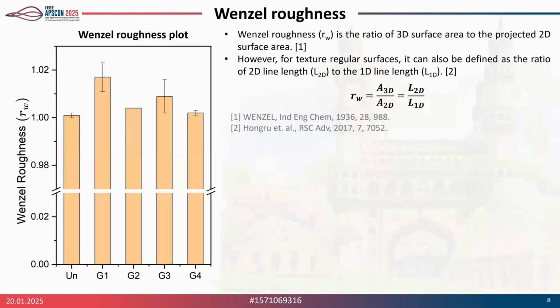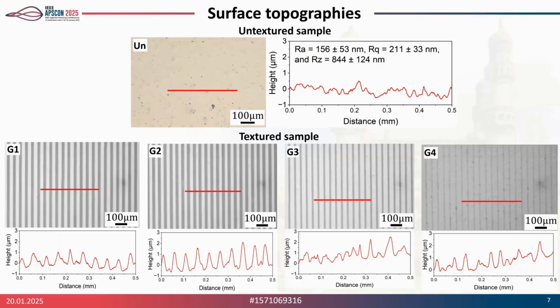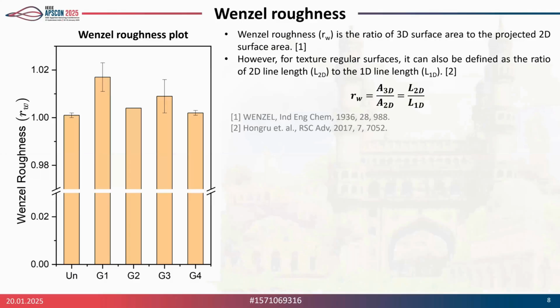So another important parameter in terms of wetting is the Wenzel roughness, which is basically a ratio of 3D surface area to 2D projected area. But in the case of a regular surface like grooves, another equation you can use is the ratio of a 2D line length to the 1D line length, wherein the 2D length is nothing but this red line, and the 1D line length is the total line scan that we use, that is 500 micron. We did 10 such line scans, and the average values of Wenzel roughness are plotted here.